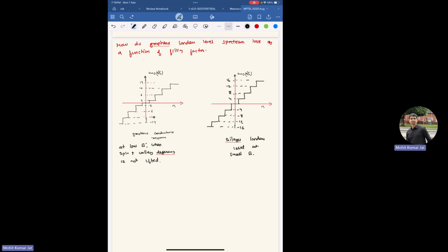That's why the linear bands have a Berry phase of pi and give Landau level spectra of 4m plus 2. Here the conductance is Gxy = ν_SLG e²/h, where SLG means single layer graphene, and Gxy = ν_BLG e²/h. ν_SLG takes values 4m plus 2, where m belongs to integers, while ν_BLG takes values 4m, where m belongs to integers.